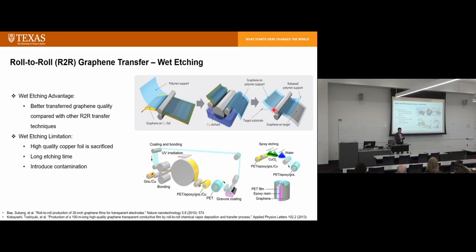However, the problem is you have to sacrifice the growth copper, which is cost, right? Production cost, and the dissolution time is long, so you have to slowly dissolve the copper. And because you use chemicals to dissolve copper, they always introduce chemical contamination on the graphene.